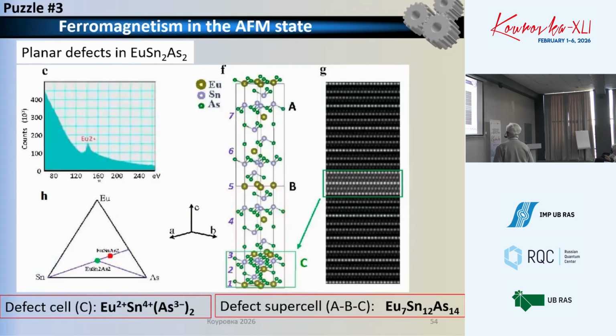Having all this data, we identified the crystal structure of the defect, and it is very interesting that it has a different formula. The formula here is europium, tin, arsenic 2. So the tin here changed the valence. Usually it has a 2+ valence state, but in this compound it is 4+. This compound is known in the literature, and it has a cubic crystal structure. To match the cubic crystal structure with the orthorhombic crystal is not easy. You have to rotate the cube and have a diagonal plane 1, 1, 1 to match the orthorhombic structure.